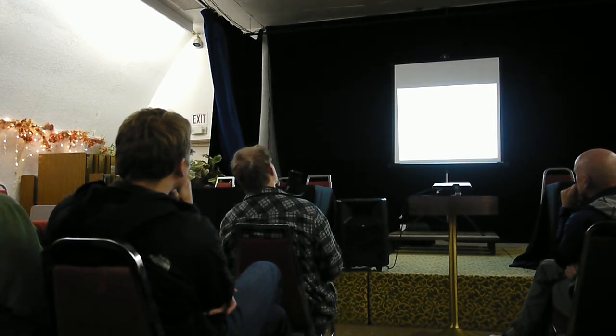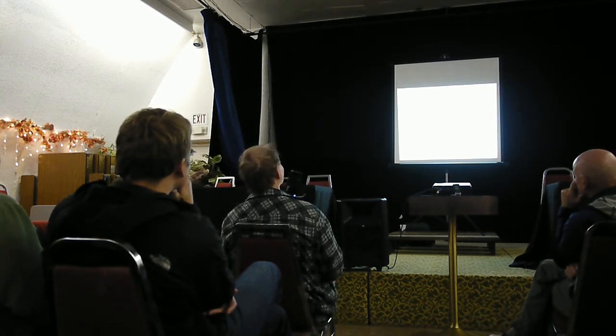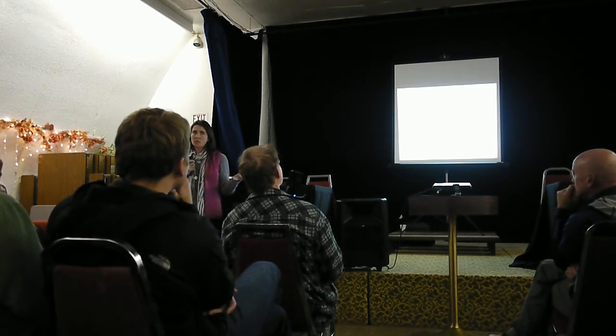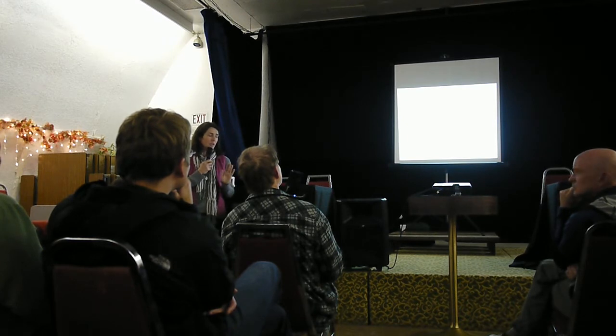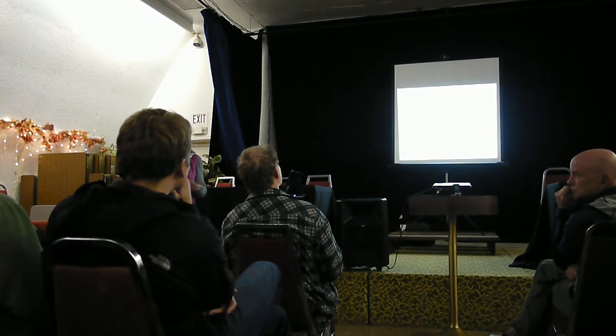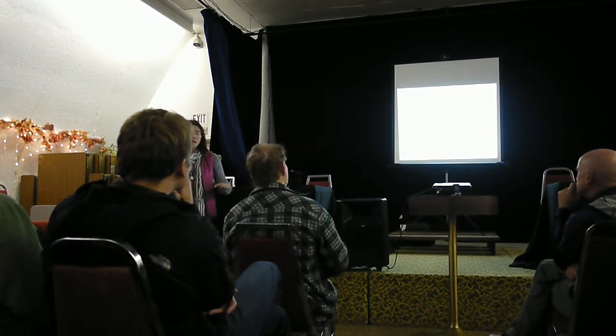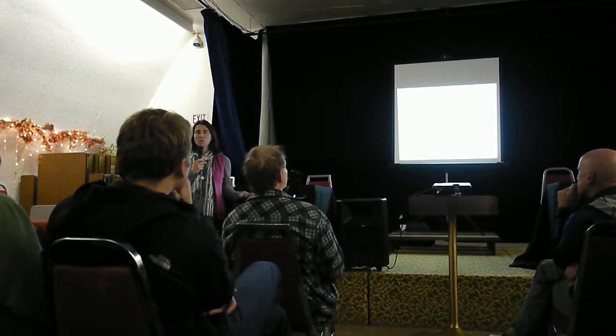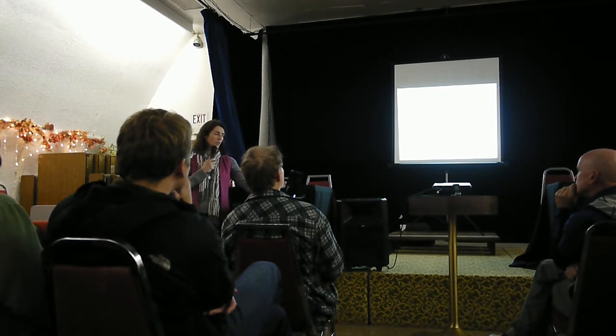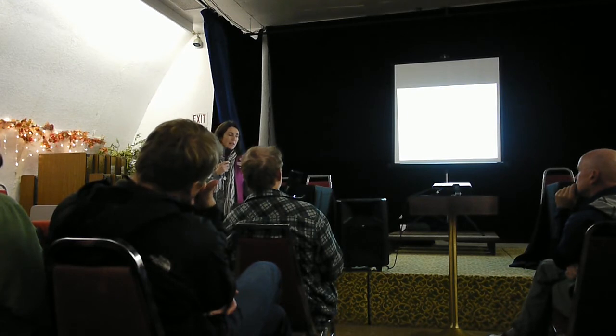This is my technical geek slide, and you have to listen to this. What they found was, and they said, you don't have to worry about this, because even though magnesium and calcium and zinc can do this, they require very low humidities in order to get that maximum concentration. So basically, each salt you can only get so concentrated before the solution can't handle anymore. The most concentrated you can get with sodium chloride is like 16%. And in order to get that number, you really need like a magical humidity of 75%.